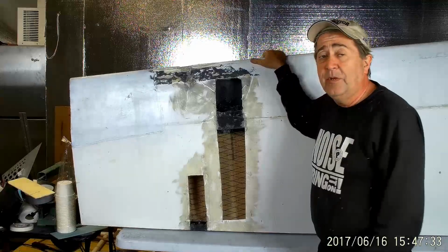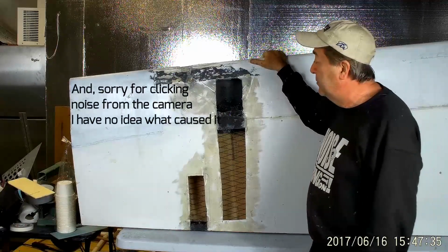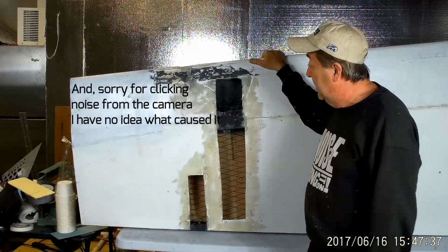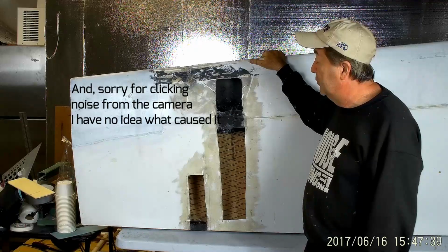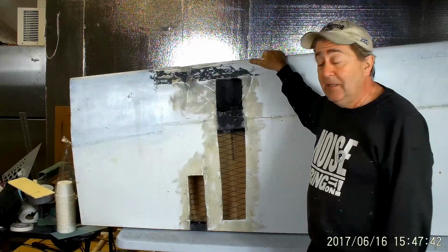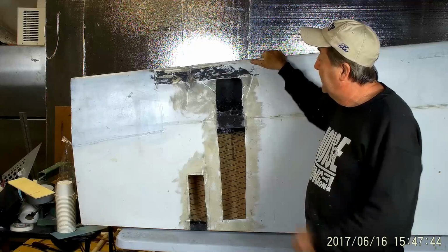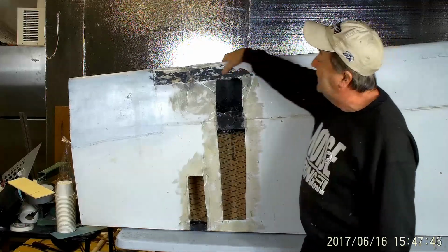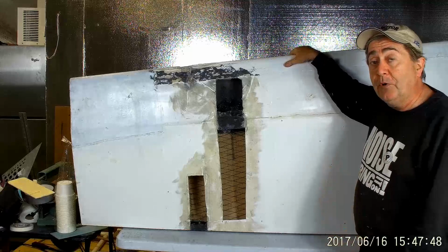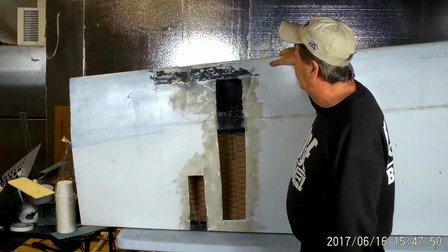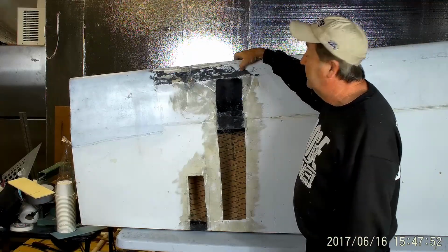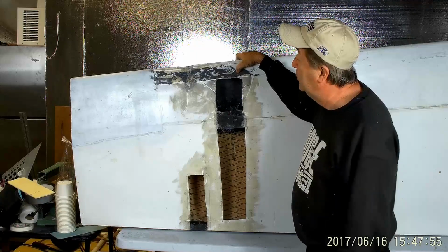This is a section of the wing that I built for testing. This has been load tested several times. It has been broken twice, and repaired 3 times. One of the repairs was this leading edge here. The early molding process that I used was not fully effective. I did not get a good bond between the Kevlar and the honeycomb core.